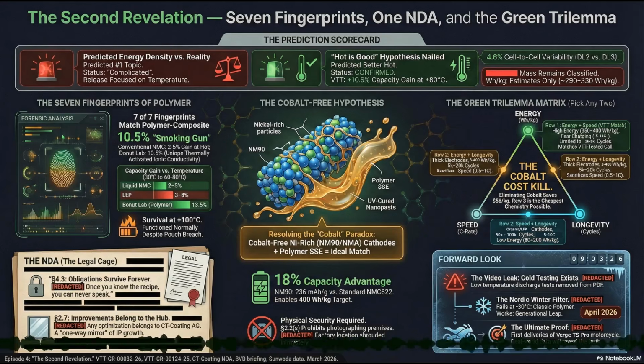29 degrees, barely above room temperature. Let's put that in context with the VTT data. In the first VTT report, the Donut Lab DL3 cell was charged at 11C with a single heat sink attached, and it reached a scorching 89 degrees Celsius. Wow. Kyle's liquid cell stayed an incredible 60 degrees cooler at the exact same relative charging speed.